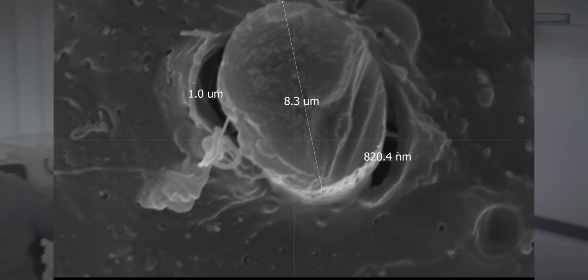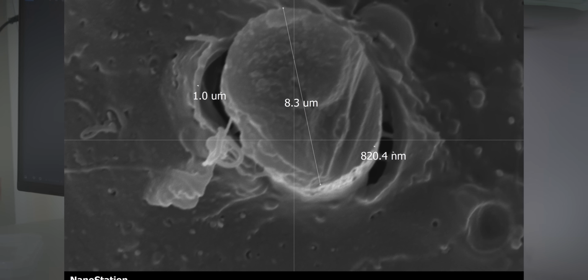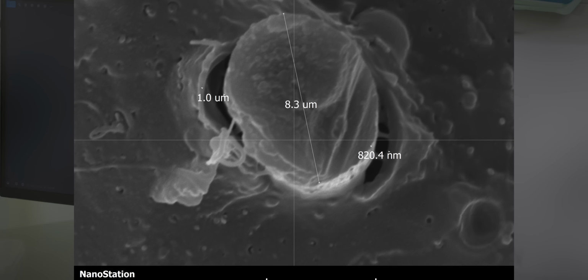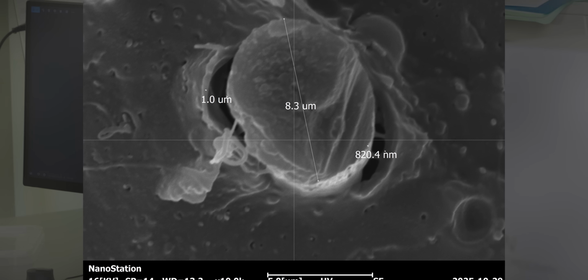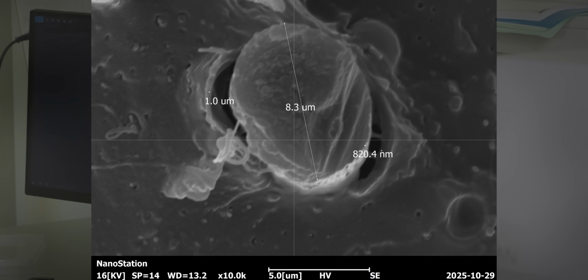So if I measure it, that's why in our last CT images you can only kind of see the gaps around the fibers, because the resolution was not high enough. The gaps are between 800 nanometers and 1 micrometer, and the fiber itself only has 8 micrometers. So that's why the resolution is pretty much not there in the micro CT.